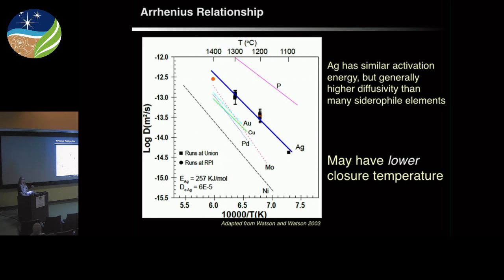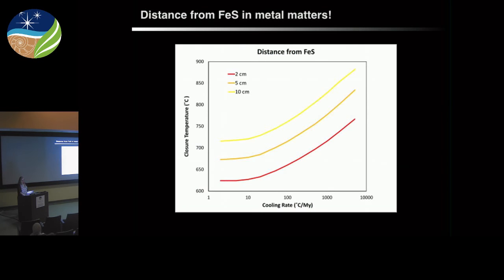The closure temperatures in the literature were based on nickel diffusion because there was no silver diffusion experimental data. I've been running the same kinds of models with the same sort of inputs as what I just described, and we've been trying to investigate what the controls on the closure temperature are beyond just grain size and cooling rates. And this is basically grain size, but there's a couple other things there. But you can see grain size has a pretty big effect.